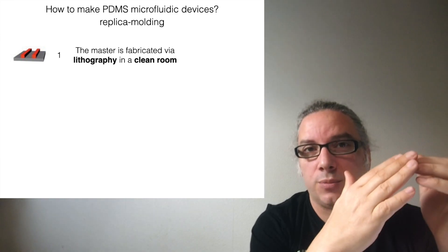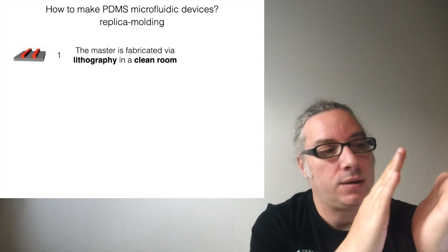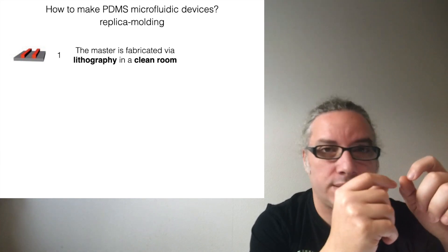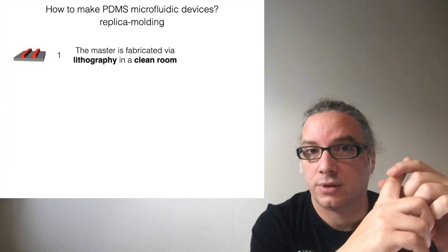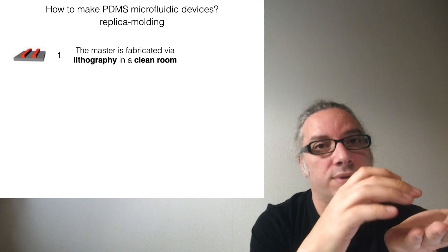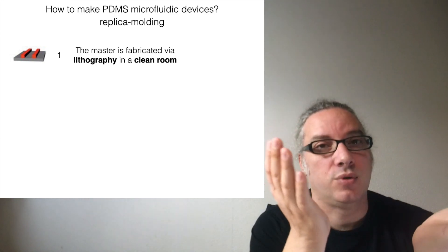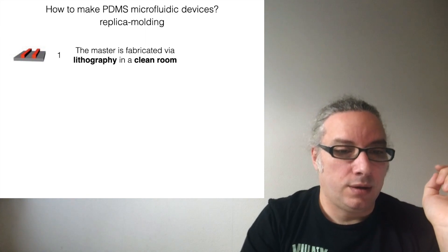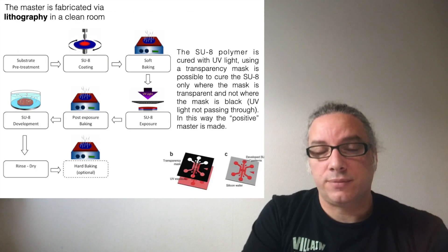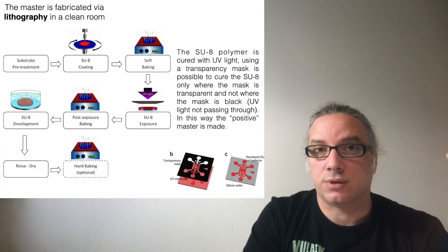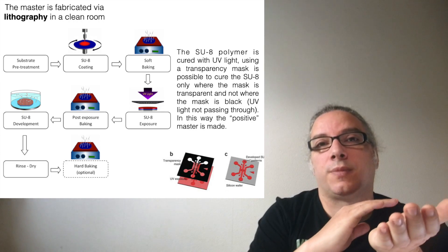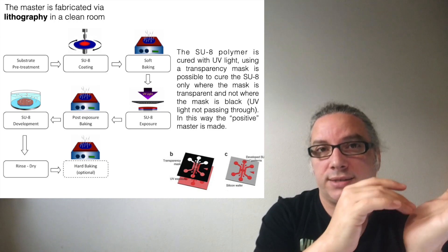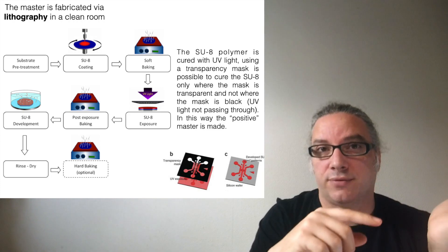This is why it's called replica molding: you need a master. A master is something we have seen with the transistor. You have a surface with something on top, you put your PDMS on top, cure it, remove it — now you have grooves on the PDMS — and then attach that PDMS on glass. For making the master, it's still a lithography method, exactly the same methodology for making transistors. You spin a substrate on top of a wafer, use a mask for curing it, remove the uncured rest, and now you have the positive part on the master.